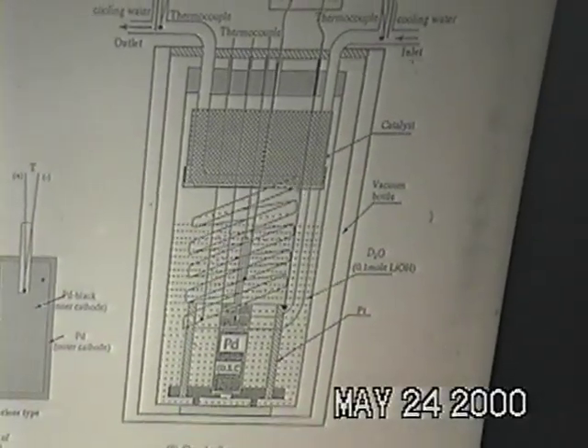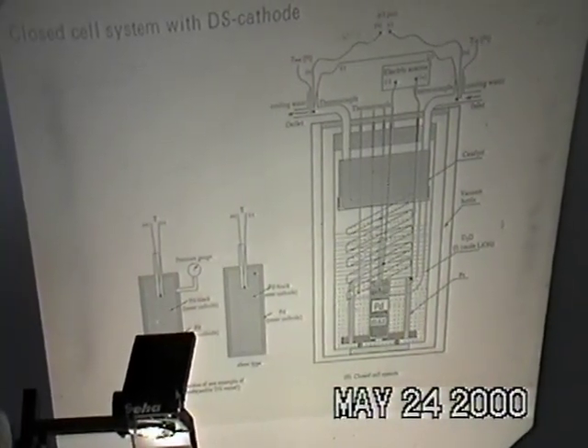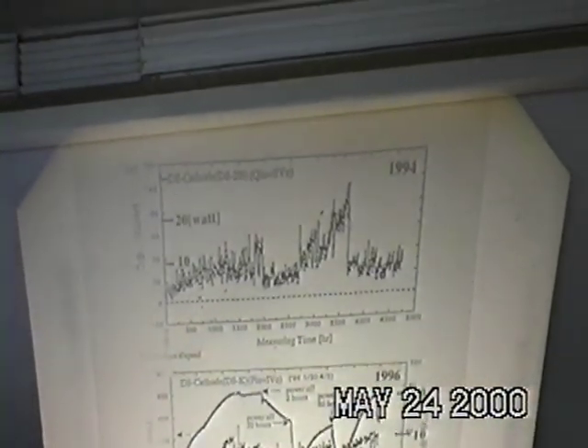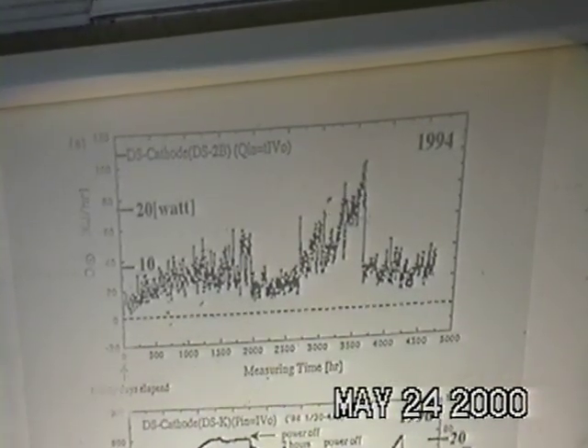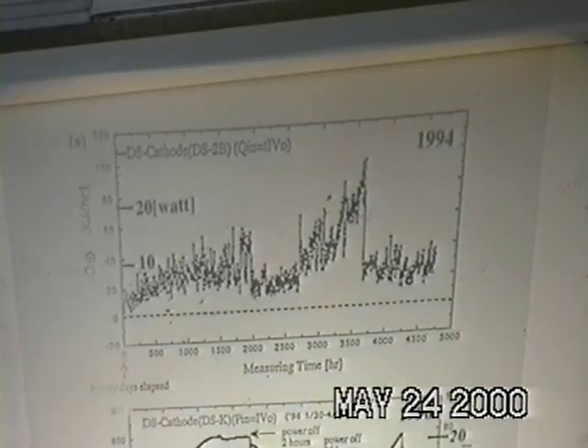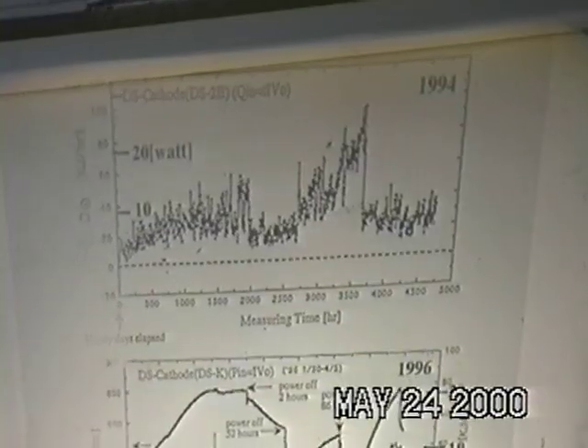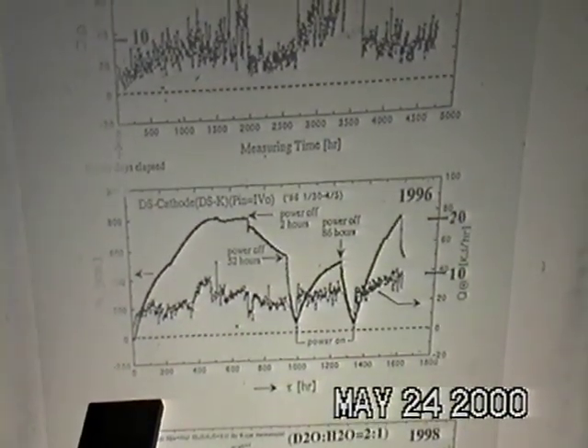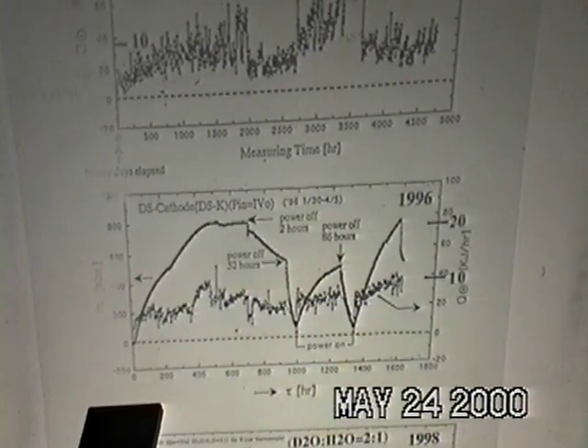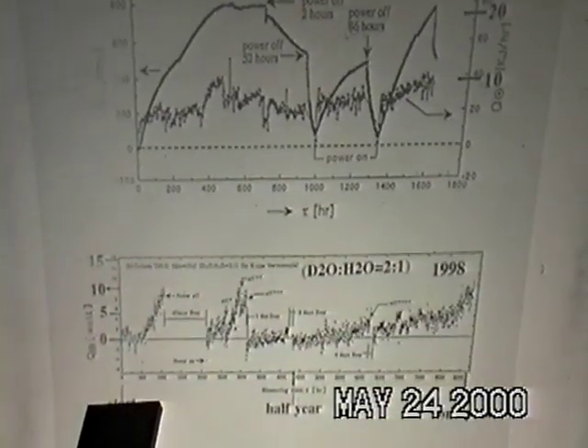This is a closed cell system we use. Left side shows both open type and closed type DS cathode. The right side shows our use. These diagrams are typical results obtained by using the closed cell system. The results have been 100% reproduced without exception. Upper data was obtained by closed system, middle data by open system, and lower data with D2O and H2O using electrolyte, in which D2O is 2 times larger than H2O in weight.